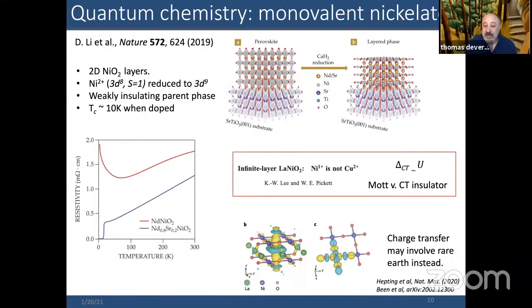But I think, as pointed out by Warren Pickett a long time ago, nickel 1 plus is not similar to copper 2 plus, at least in lanthanum nickel O2, in the sense that the oxygen lies at much deeper binding energy. The charge transfer energy to the oxygen is roughly on the order of 4 to 6 electron volts below the Fermi level. And the Hubbard U is maybe on that order or even less than that. So that's more like a Mott insulator.